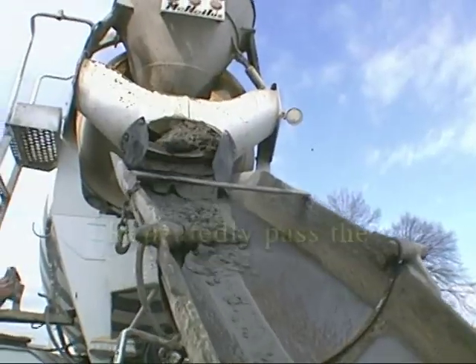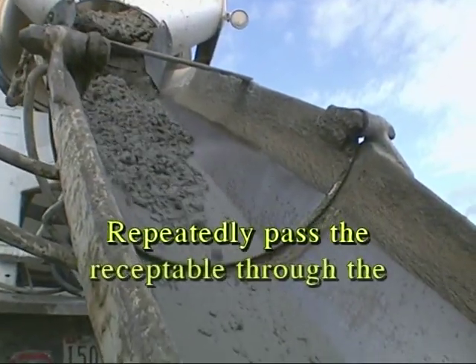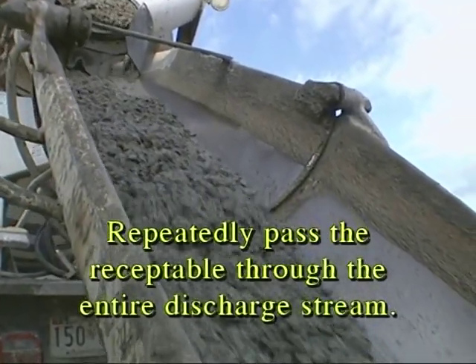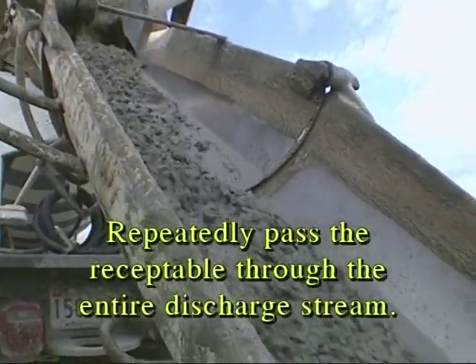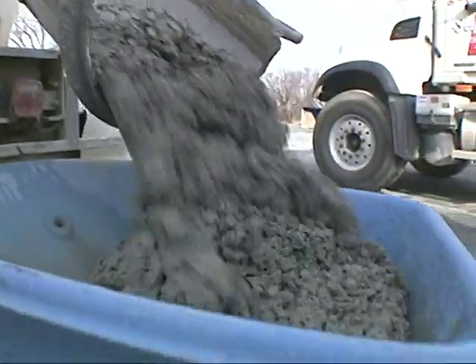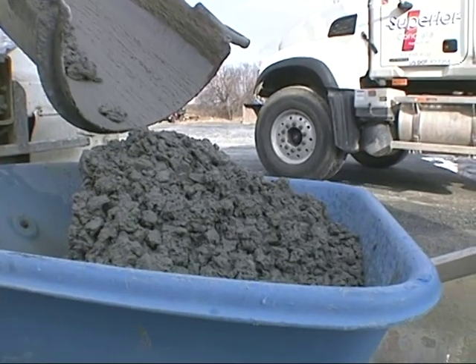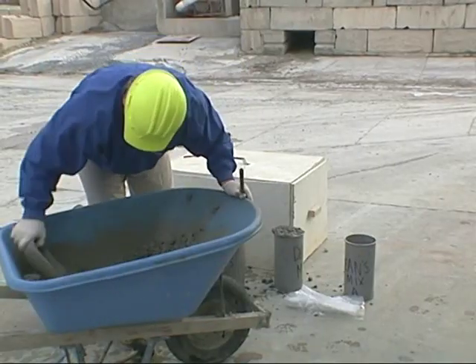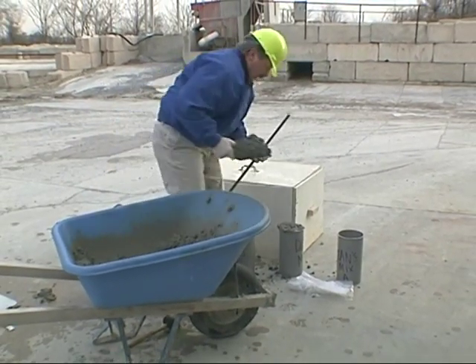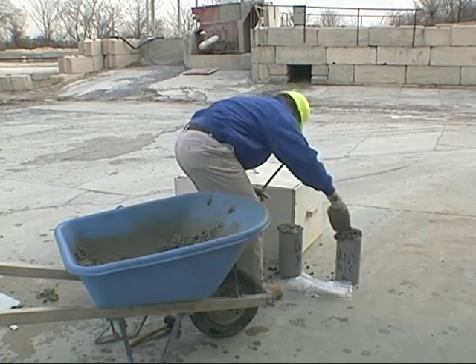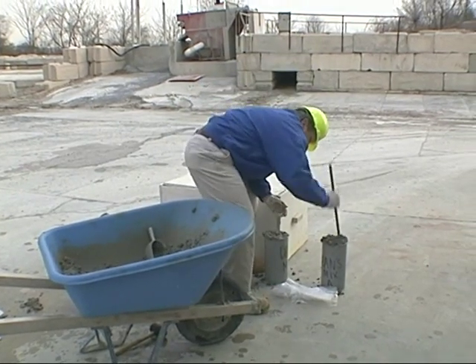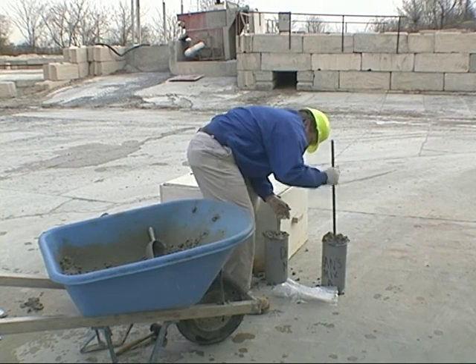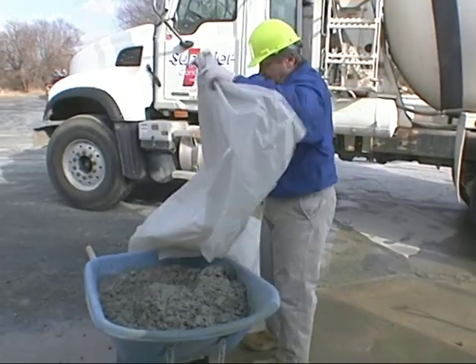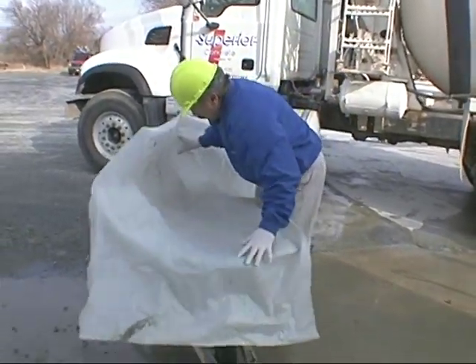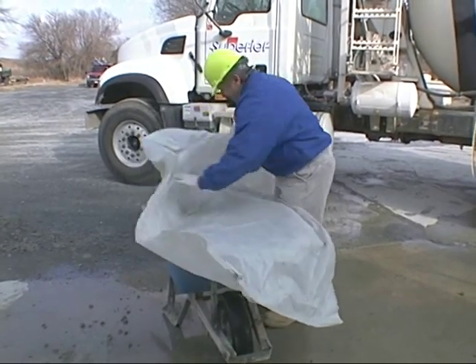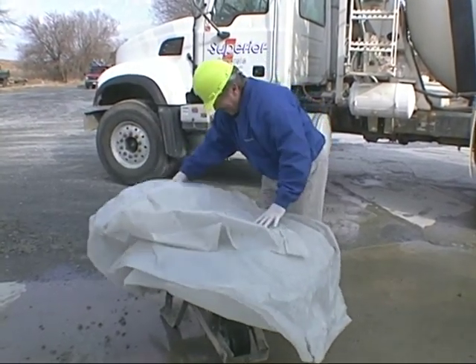3. Repeatedly pass the receptacle through the entire discharge stream, or completely divert the discharge stream into the sample container, in this case, a wheelbarrow. 4. If making concrete cylinders, a minimum of 1 cubic foot is required. 5. Make sure the sample container is covered to protect the concrete from the elements.